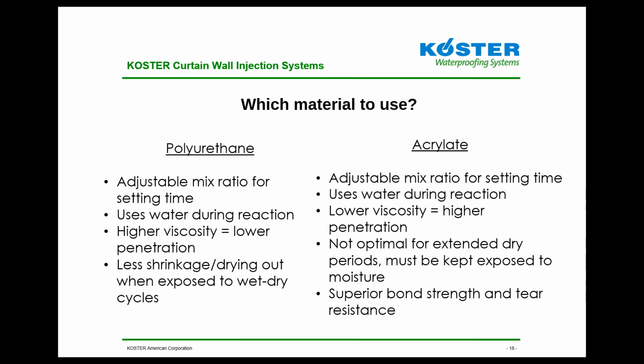Acrylates are generally better at penetrating through water immediately after injection, based on a chemical compound which allows the material to cut through water, preventing it from being washed away as easily in a situation with moving water behind the wall or an active leak. The higher viscosity of the polyurethanes means less penetration generally into substrate voids and soils. This means polyurethanes are generally less effective in soil stabilization, but also means the material often cures in place without the risk of the gel traveling too far before the reaction begins.